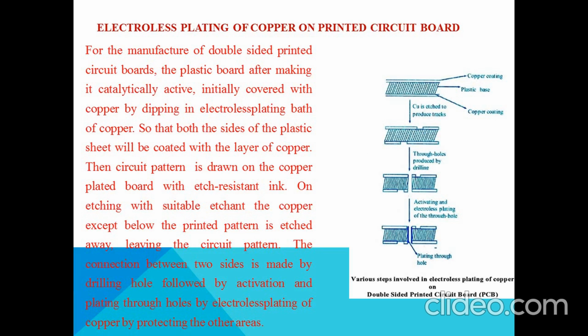In this slide, we will discuss the various steps involved in making a PCB. Initially, a plastic board is taken and that is made catalytically active and then dipped in the electroless plating bath of copper, so that both the sides of the plastic board will be coated with a layer of copper. Then the circuit pattern is drawn on the copper plated board with etch resistant ink. On etching with a suitable etchant, the copper except below the circuit pattern is etched away, leaving only the circuit pattern. Then the connection between two sides of the board is made by drilling a hole, and then that hole is activated. After activating, the hole is plated with electroless copper by protecting the other areas.